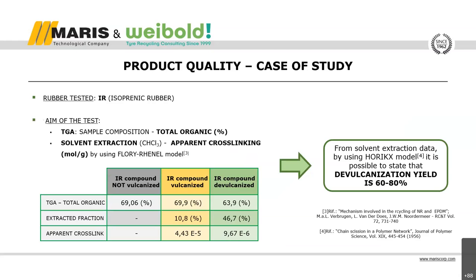an anti-sticking agent. The extraction analysis is used as an indicator of the fraction of devulcanized rubber. Briefly, if there aren't cross-links between the chains, like in the virgin rubber not vulcanized, the sample is completely soluble in the solvent. If there are cross-links between the chains, like in the virgin vulcanized rubber, the sample tends to swell and only the other components of the formulation are solubilized. In this case, we obtain 11%. After the devulcanization process, the cross-links between the chains are selectively broken. In this way, the soluble fraction increased to 47%.